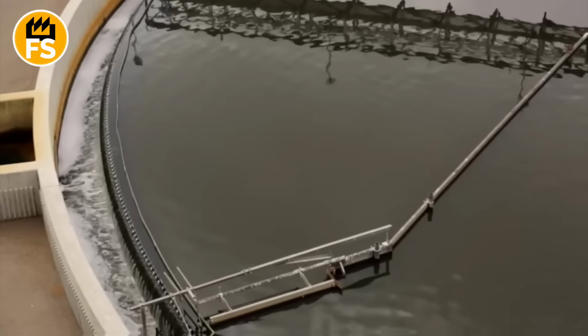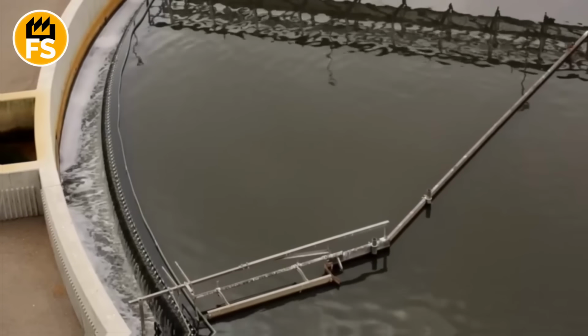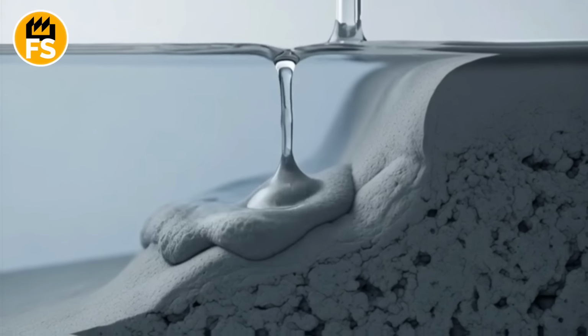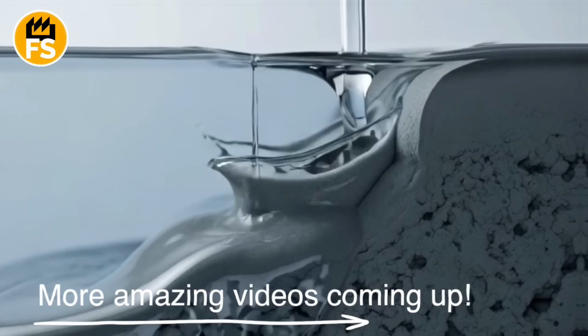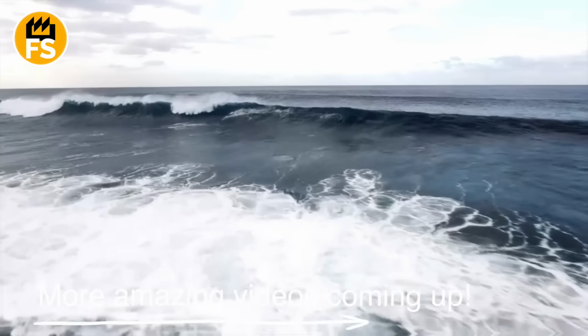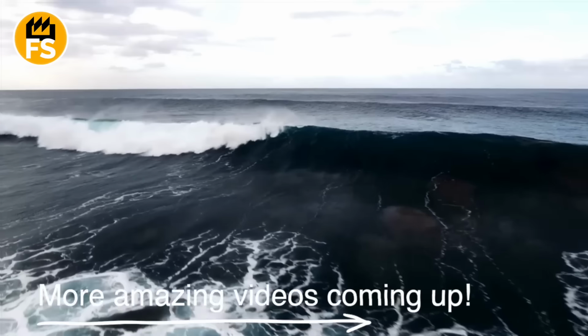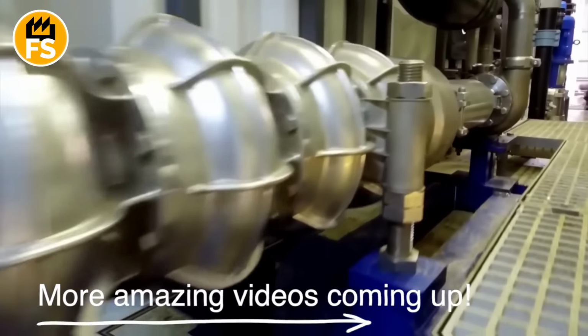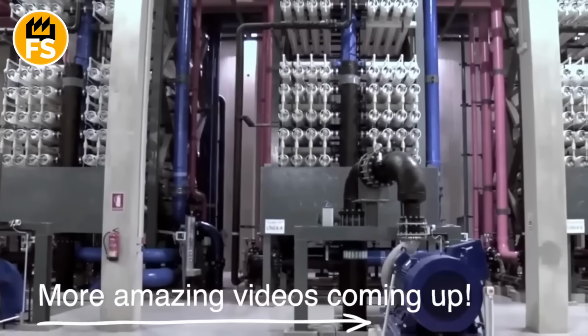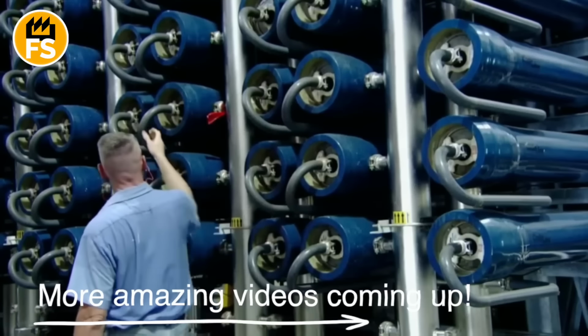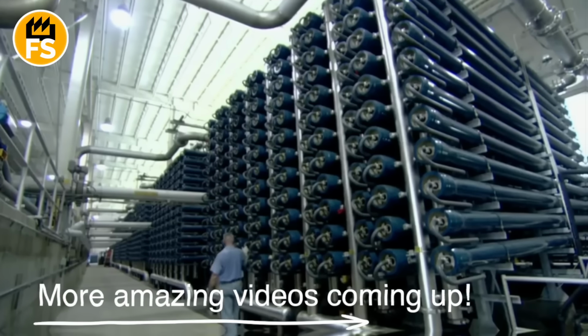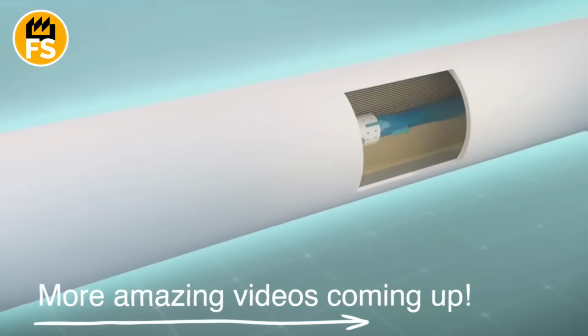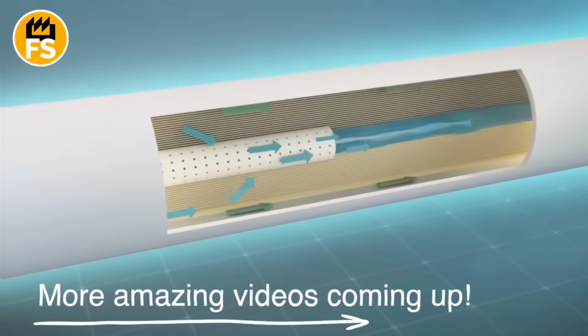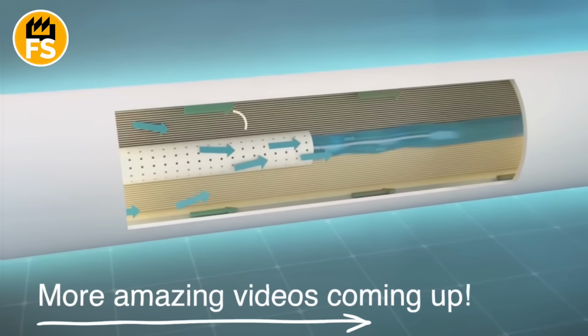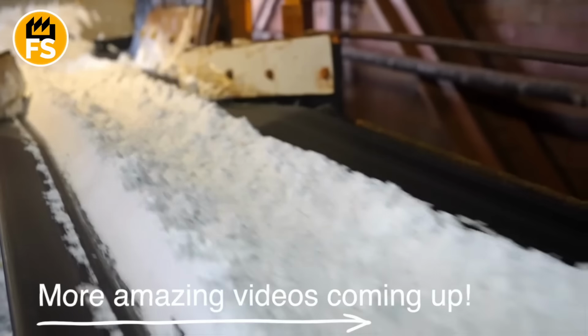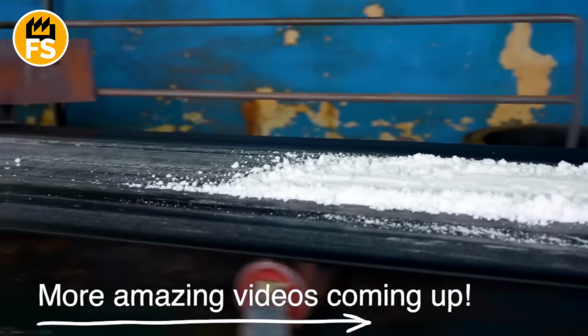There it sits for several hours, and the solid fraction slowly settles, forming a dense layer that looks like wet cement. The upper part of the water is drained back into the sea or directed for retreatment, while the sediment is collected by special grabs or vacuum systems. Then, the sediment is rinsed with fresh water and dried in powerful drying ovens that blow hot air at speeds capable of removing an entire layer of moisture in a minute. When the mass becomes brittle, it's moved to roasting furnaces.